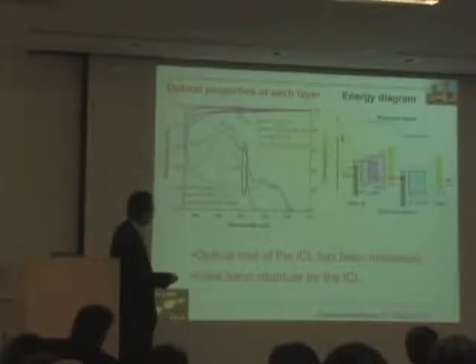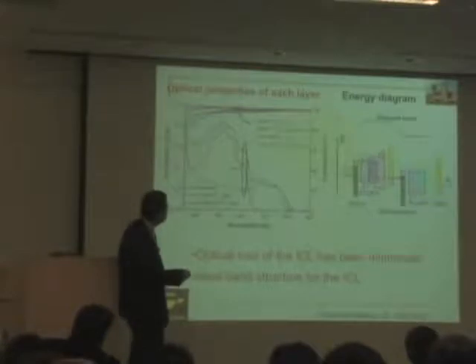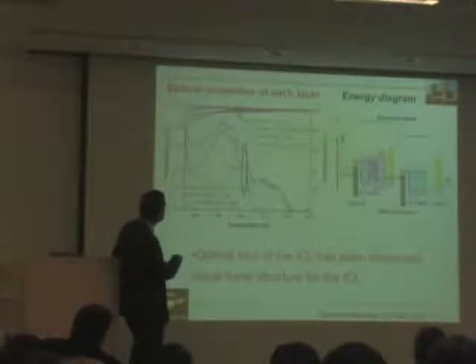So you can see the front cell and the back cell, and then the interconnecting layers. For the interconnecting layers, this is the absorption. You can see how transparent this is, with a transmission of almost 100% across the absorption of the solar cell. So this is sort of the criteria of the interconnecting layer from the physics point of view.